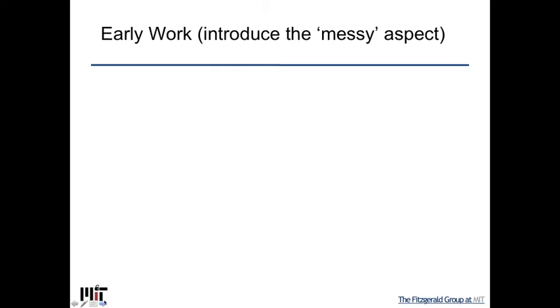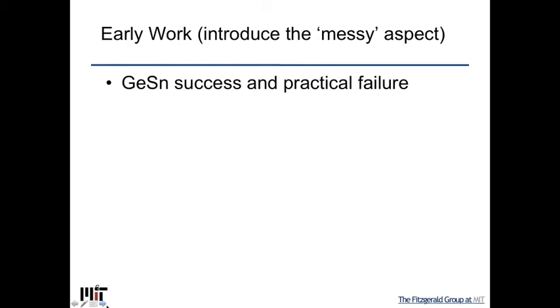It dealt with lattice mismatch, but it also dealt with something called phase instability, quite an advanced, complicated problem where we were trying to create germanium tin alloys. But it's a very interesting story of how corporations dealt with early fundamental innovation. We actually had success. Nobody had been able to make germanium tin alloys before. And so we were the first ones to make them with significant amounts of tin in them.